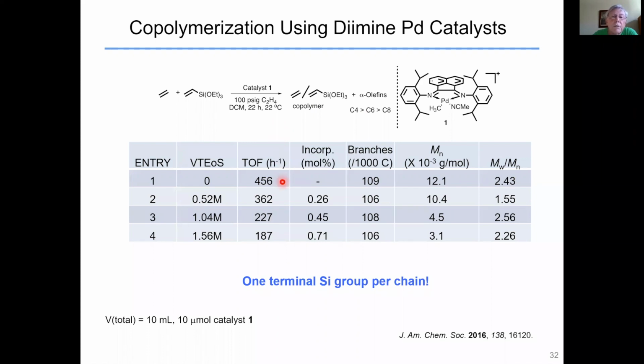If you look at the turnover frequency, as we increase the vinyl triethoxysilane, the turnover frequency drops, but not precipitously. And if you also calculate in the alpha olefin products, the turnover frequency actually stays basically the same. As you increase the vinyl triethoxysilane, you see more alpha olefin product. And of course, the incorporation tracks the concentration of the vinyl triethoxysilane. You get highly branched materials, and the molecular weight drops as we increase the vinyl triethoxysilane concentration. If you look closely at this material, you get one terminal silyl group per chain. So we're only getting one trialkoxysilane group per chain. So how is this working?